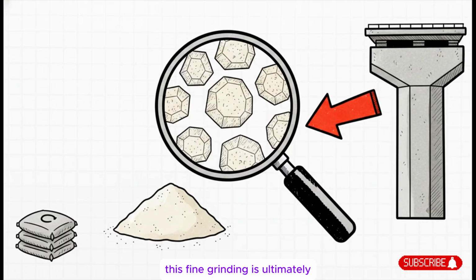This fine grinding is ultimately what builds out our final product specification. The finished Portland cement is milled to a highly specific fineness, giving it a target-specific surface area, known as Blaine's value, of approximately 225 square meters per kilogram. This vast surface area is exactly what allows the cement to hydrate properly and gain its incredible strength. Once it hits that precise target, it's pumped straight into silos for bagging and bulk dispatch.